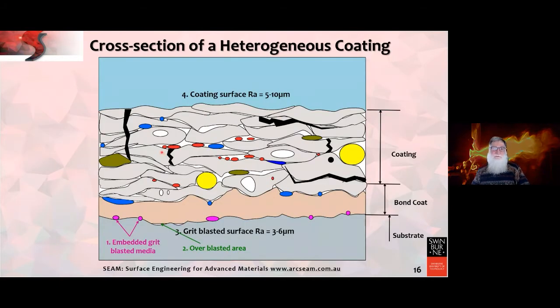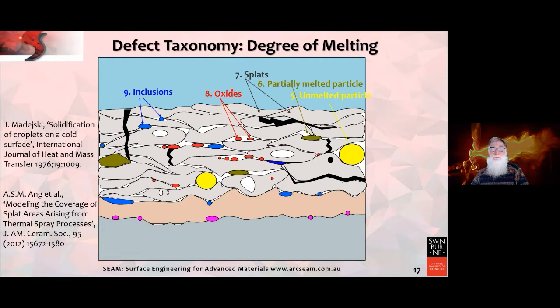So here's a cartoon. These coatings are heterogeneous, they're anisotropic, and that leads to variable properties, which can either be good or bad, depending on the application. But again, I'm pointing to embedded grit blast media. Some places may be overblasted. We see the coating and we see all of these defects. And the coating roughness is typically about 5 to 10 micrometers. We also have the degree of melting. So we have inclusions, oxides, splats, partially melted particles, unmelted particles.